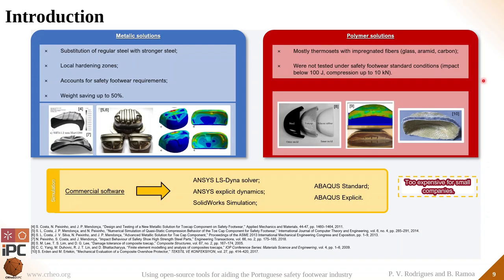There are several reports in the literature that present studies on metallic toe caps using commercial software, and they have interesting results, such as substantial weight reduction up to 50% by using stronger metallic alloys and local hardening zones, and this can allow the development of new designs. For non-metallic solutions, we could only find reports related to material development, mostly with thermosets with impregnated fibers, like glass, aramide, or carbon fibers. But these reports tested the toe caps under conditions below the standardized conditions for safety footwear.